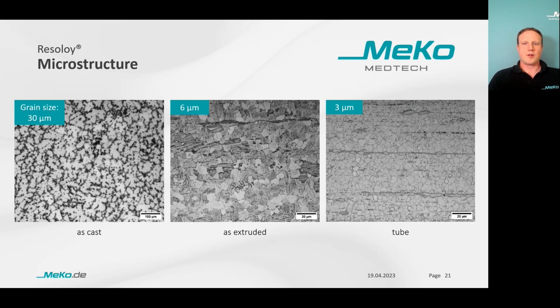These images are showing the microstructure of Resoloy after each process step, with comparatively large grains after casting on the very left side to a fully recrystallized fine-grained structure after tube extrusion on the right side. The average grain size is about 3 microns in the tube state. And this microstructure results in the following mechanical properties.